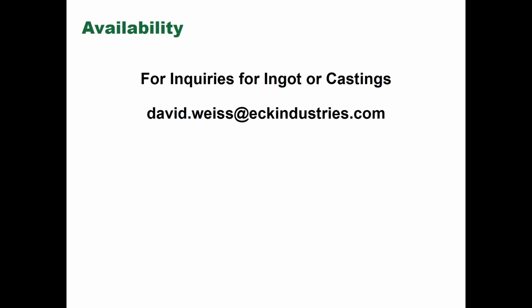The answer is no. We're preparing a paper for Casting Congress coming up in 2017, and we talk more extensively about that. There were a couple of things when we did our initial pilot scale production. We produced 700 pounds of the material. Initially we added the magnesium to alloy it up, and then we added the cerium to the desired level. The cerium somehow prevents gas pickup, or at least reduces it, and reduces dross formation.